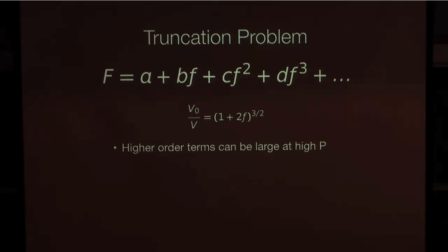So as we get more and more precise measurements at high pressure, say at 20 gigapascals, would it not make sense to use that as a reference state rather than ambient conditions? Yes, there is an attempt for that too. Barbara made a great point that the V naught or K naught, the notation of subscript naught, is arbitrary. You can actually set, for example, 20 GPa as your reference point.